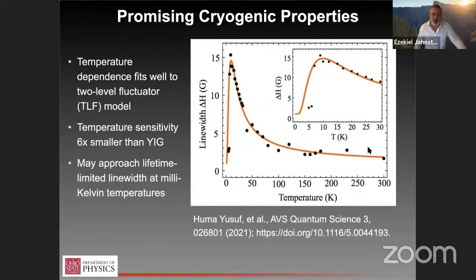But sort of in broad strokes, you can think of this high temperature regime where the line width is increasing as arising from the fact that at room temperature, our paramagnetic spins are perfectly unpolarized. We have just as many spin up as spin down, but only one of those two spin orientations can scatter magnons, because all our magnons essentially have the same angular momentum, either +1 or -1, depending on the direction of the magnetization. So only half of those spins can contribute to spin magnon scattering, because for the other half, the angular momentum would not be conserved. But as you cool it down and those paramagnetic spins polarize, more and more of those spins are in the state that can scatter magnons.